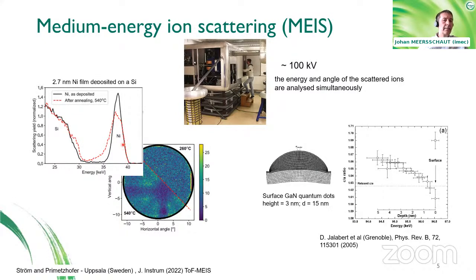So from fitting and analyzing the spectral shape of the particles that are being scattered on the sample, you can derive something about the depth profile of the nickel on this silicon sample. Important is also that the backscattered particles in such a medium energy ion scattering experiment have rather low energies and can be treated with electrostatic and magnetic fields easily. And this allows to obtain full 2D maps of the particles as a function of energy and angle of exiting the sample. So here you see such a 2D map as a function of the angle, as the particles exit from the sample.